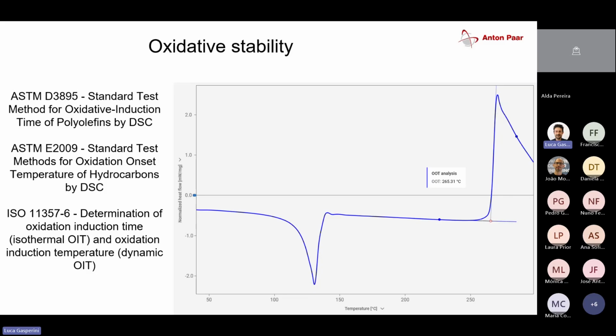So in this case, we have an LDPE material. We perform the OOT analysis, oxidative onset temperature. This is a simple experiment. You just take the sample from room temperature under the atmosphere of either air or oxygen. Air is considered an oxidative atmosphere. Although it's only 20% oxygen, that's good enough for oxidation to happen. And we heated the sample up. At a temperature of about 120 degrees, we actually see the sample melt. And then at a temperature of about 265 degrees, we see a strong exothermic effect, meaning that the oxidation in the sample has taken place. It has changed the sample irreversibly. And we might say that the oxidative onset temperature of this sample is 265 degrees.